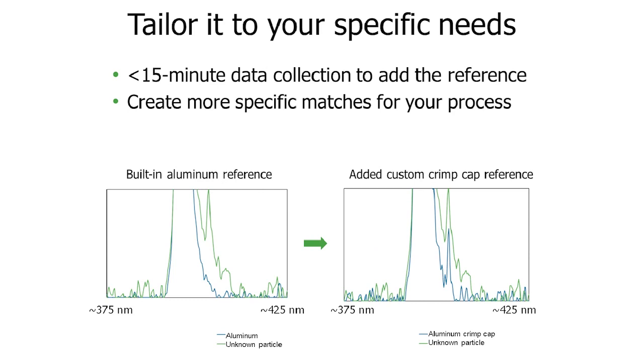Let's talk a little bit about why you might want to customize that database. Doing this allows you to get a highly specific match for a particle. For example, our database has aluminum in it, which is shown on the left. But a specific brand of crimp cap that you use in your process could have a unique peak like the one seen here on the right. While both spectra are aluminum, the custom reference spectrum allows you to get a much more specific match to narrow down the exact source of your particle.